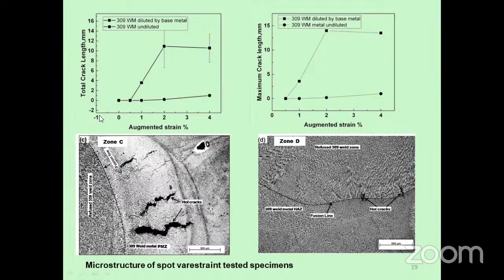Here, after doing the spot Varestraint test, we have seen that where we tested very near to the weld interface, we see very high cracking susceptibility, whereas at the weld metal center, we see very negligible cracking happening. So this is the macrostructure where we did the experiment near to the weld interface, that is, where this base metal dilution is there. So here we see very large cracks on the surface, and where there is negligible cracking, here we don't see any cracks on the surface of the weld metal.